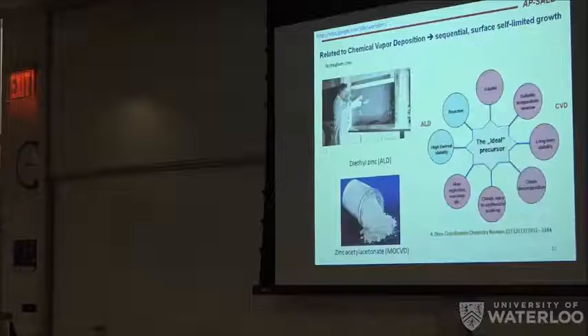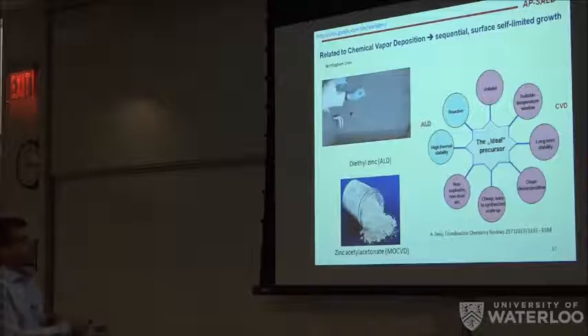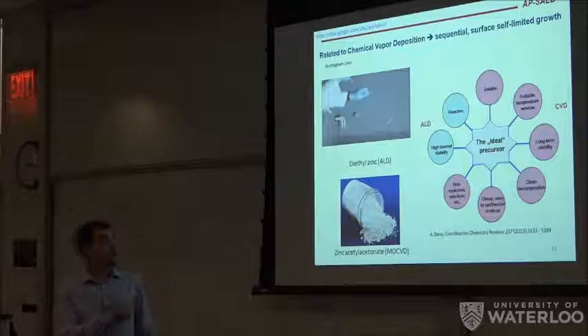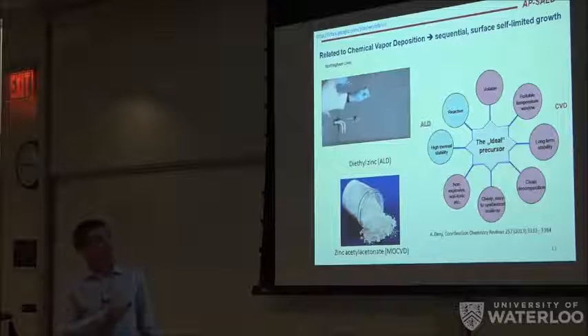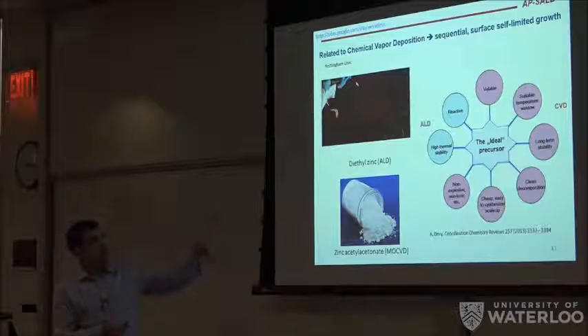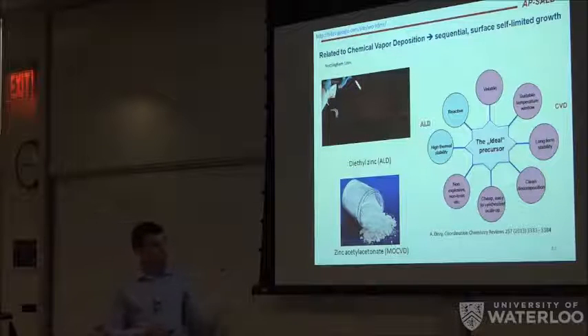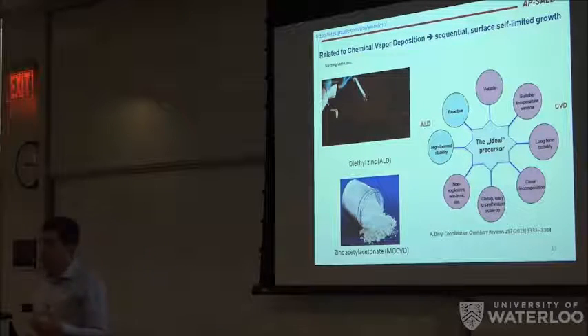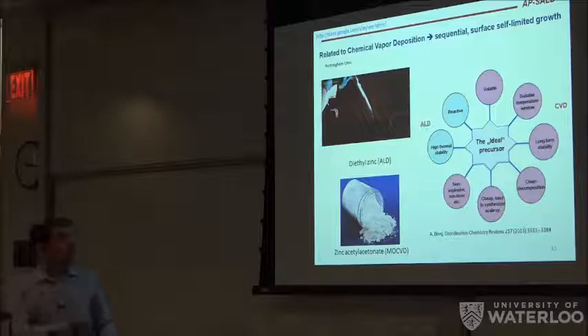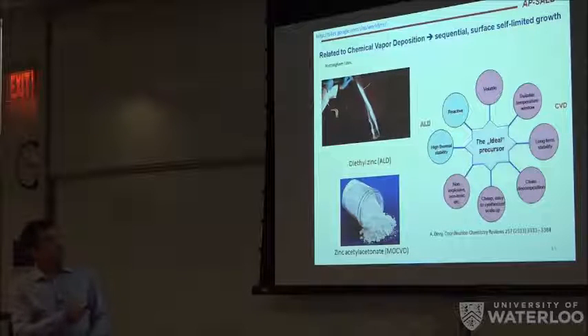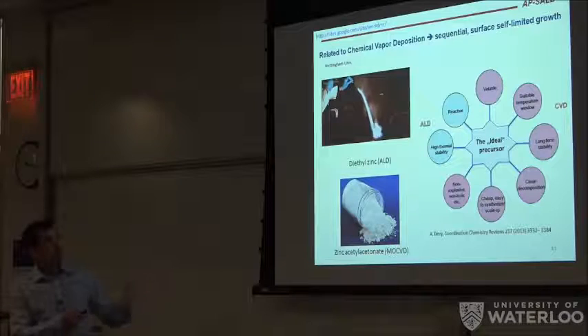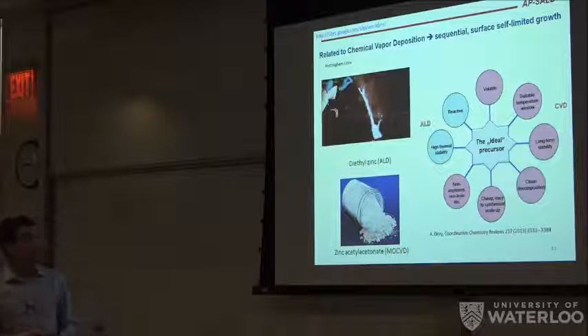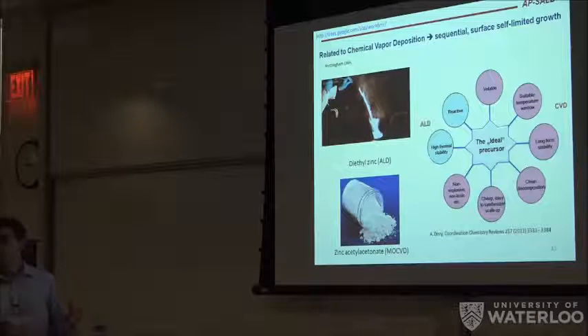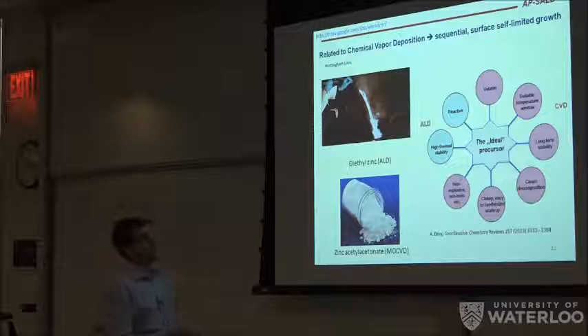And this is due to the chemistry which is behind, and it's due to the precursors being used, which are, in this case, very reactive. If you compare an ALD precursor with a CVD precursor, you can see that the CVD precursor is quite stable. You can handle it in the open air, while ALD precursors are more reactive. In this case, it's the diethyl zinc, a typical precursor for growing zinc oxide, which is pyrophoric, which will catch fire the moment it sees the air or water.